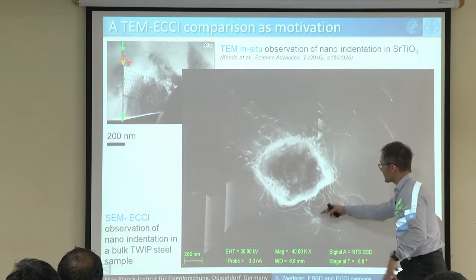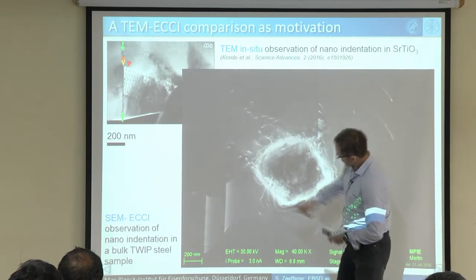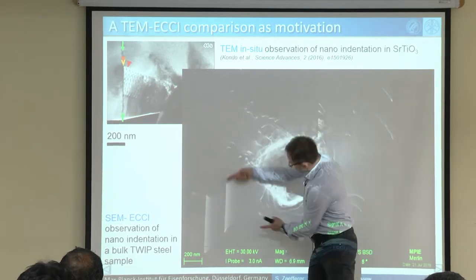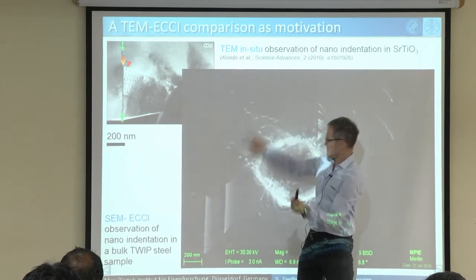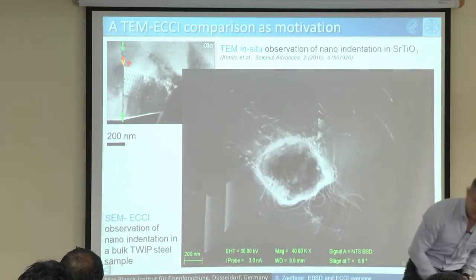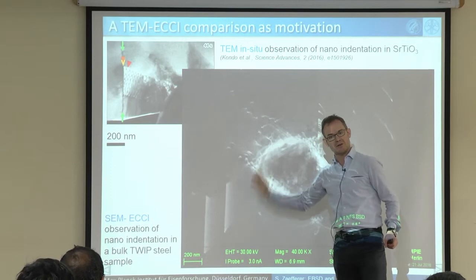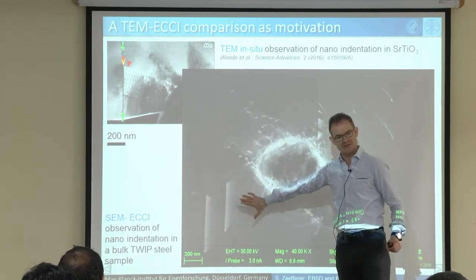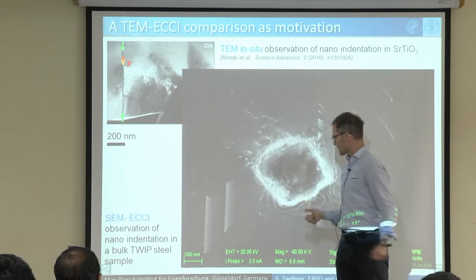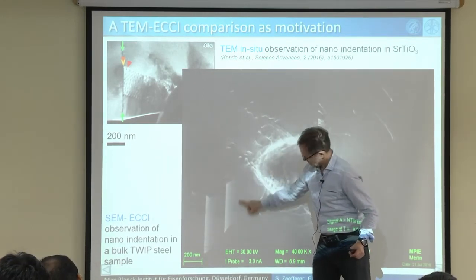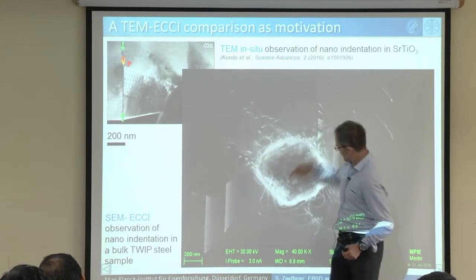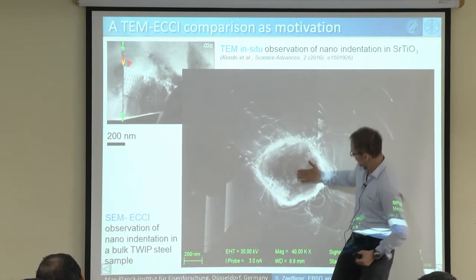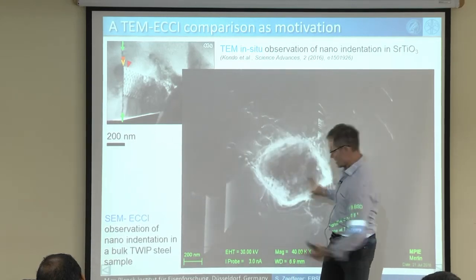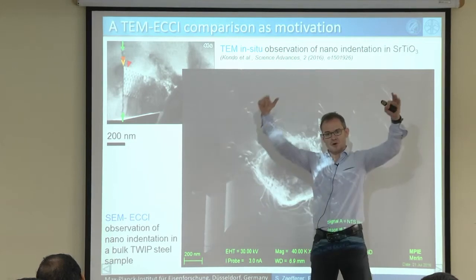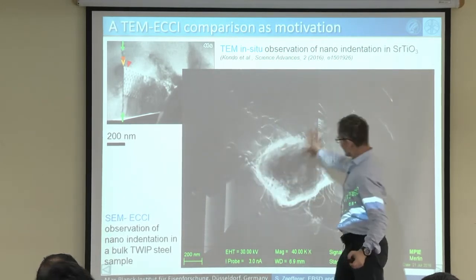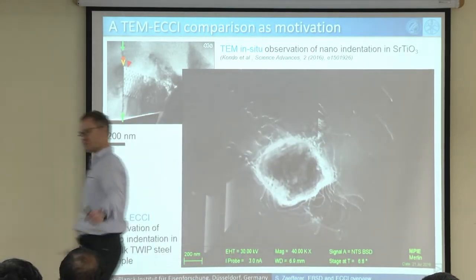Yeah? Here's one source emitting dislocations. Here's another source emitting dislocations. This one here is stacking faults, which actually, here's a partial dislocation, here's a partial dislocation. Between them is a stacking fault. And if you look on my computer, you see actually the thickness fringes as you would see them in a TEM as well. So it's the same picture as in a TEM, just from a bulk and not from a thin foil. And these stacking faults come from a slip system which has been activated deep below the indent, and then they come out under a certain angle, at a distance of 400 nanometer to the center, to the surface.